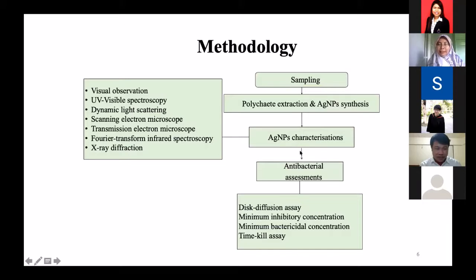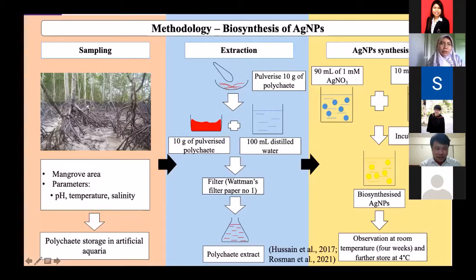After we validate the silver nanoparticle formation, we can do the antibacterial assessment using four methods known as the disc diffusion assay, minimum inhibitory concentration, minimum bactericidal concentration, and also time kill assay. As I mentioned earlier, we need to go sampling. We need to collect the sample from the mangrove area. Normally, we also collect some data from the sampling site. Then we also maintain the polychaete in artificial aquaria and also in our hatchery. Then we do a few steps in terms of extraction. Here I can show you that we use only 10 grams of polychaete and add 100 ml of distilled water.